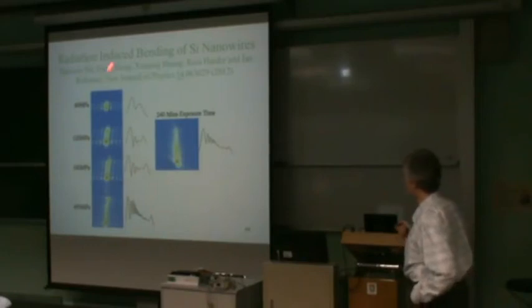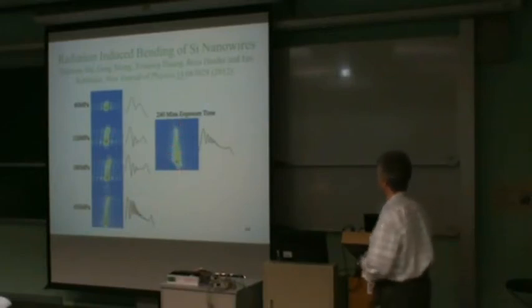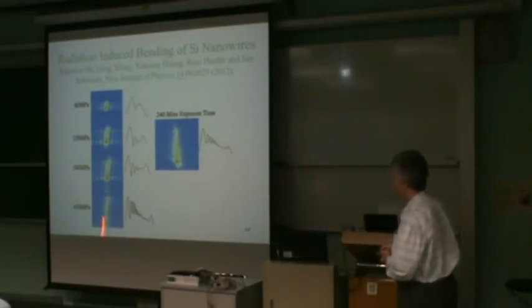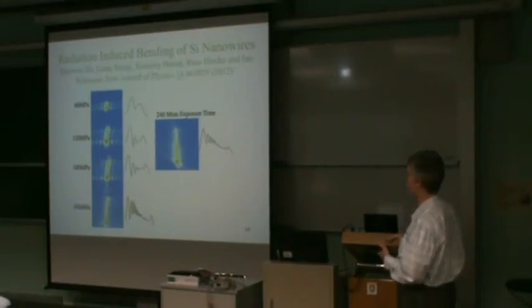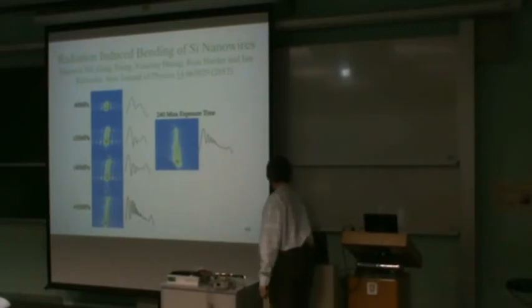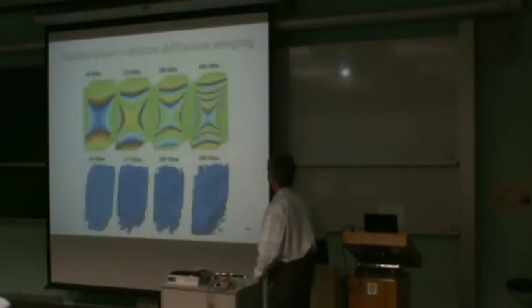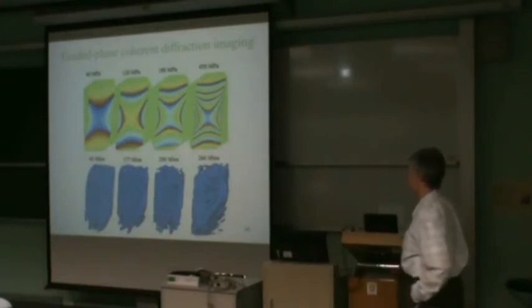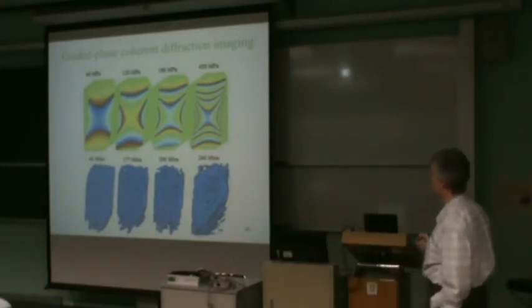And the calculated diffraction patterns look a lot like the experimental one that we saw at the largest time. So we've got this quite similar appearance of the diffraction patterns. So what Xiaowen then tried to do was to use these best guess diffraction patterns as a starting point for the phasing algorithm to actually go in and phase this diffraction pattern, which is otherwise impossible to phase. And she came up with a new method called a guided phase error reduction algorithm was the name that we finally settled on.